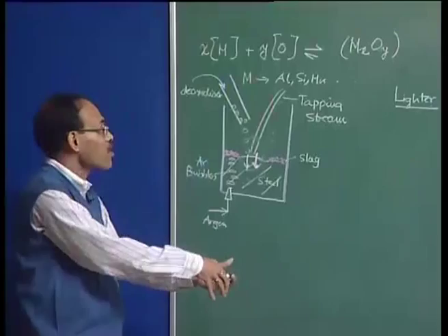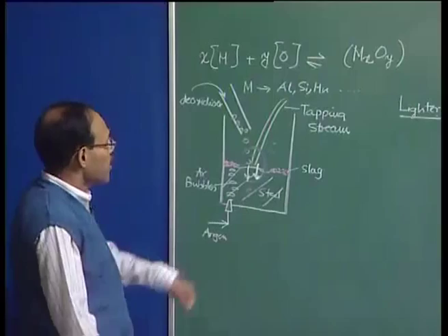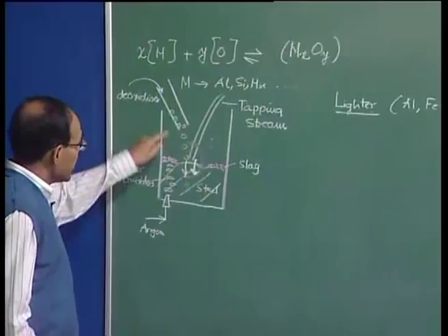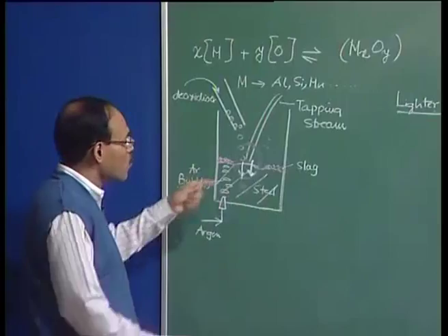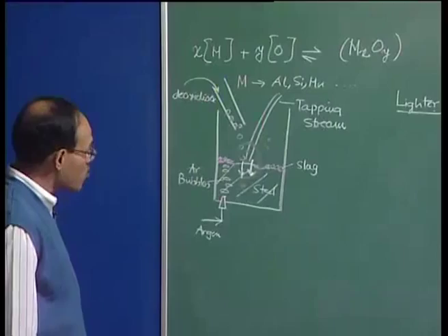The oxides are always lighter, that is why the oxides of the slag are going to float up, and the amount of the slag is going to be progressively building during the process of the ladle filling operation as well as deoxidizer element addition. So, deoxidizers upon their entry into the bath will spend some time subsurface, and in the process they are going to melt and dissolve and react with the oxygen in the bulk steel. This we say is the deoxidation product.